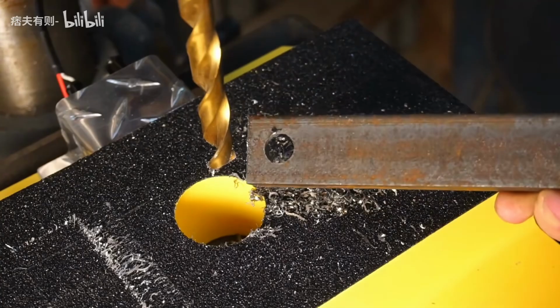Why are there cracks? Maybe the internal resin thickness is different, caused by uneven shrinkage during solidification. The solution is also simple. Readjust a bit. Slowly fill the gaps. It's rock solid after 48 hours. The mold can be removed. Remove the round tube. Then knock off the acrylic sheet on the bottom. Take it easy. Don't break it. It's really stuck. Finally broke it.